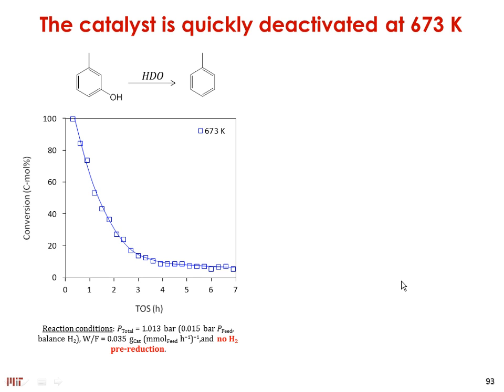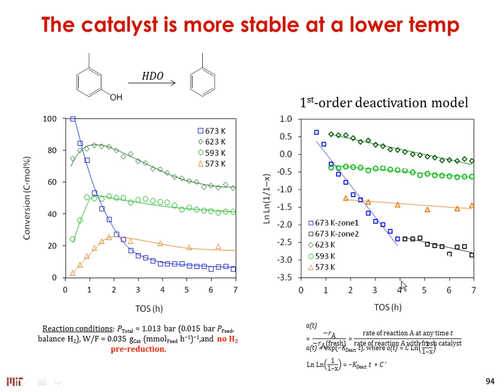In addition to this phenomenon, if you operate at 673 Kelvin, at 400 C, the deactivation is very drastic. You lower the temperature, and you start seeing this induction period on the catalyst, followed by a much flatter rate of deactivation. We see that this is the 400, first order deactivation rate, and these are the other ones at a different temperature. And we start asking, what is going on? Why do we have this induction period? What is happening on the surface?